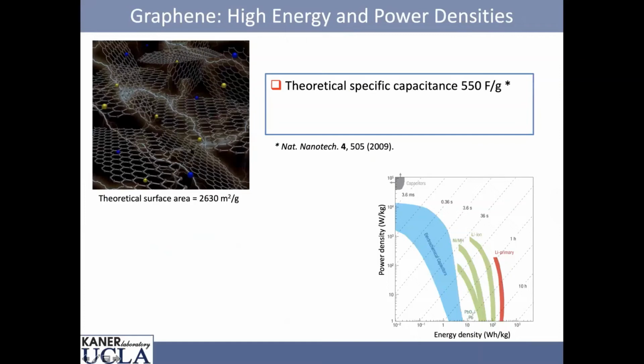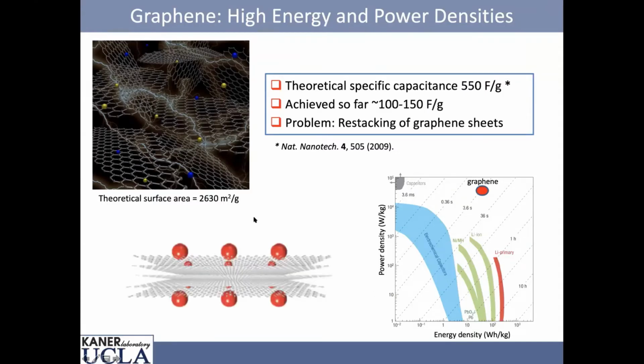What's interesting is graphene could, in theory, solve this problem by itself. It has a very high theoretical specific capacitance, about 550 farads per gram. Trouble is, if you actually go, so here it is on this chart, but when you actually go to make these devices, you only get about a quarter of that, about 100 to 150 farads per gram. And the problem is the restacking of graphene. So the surface area of a graphene sheet is 2,630 meters squared per gram, but that's assuming you can address the top and the bottom of the sheet. If you put two sheets together, you lose half the surface area per gram, so it dropped to 1,300. And so until we did our work, there was no way that people could figure out how graphene would not restack when you stuffed it into an electrochemical device.